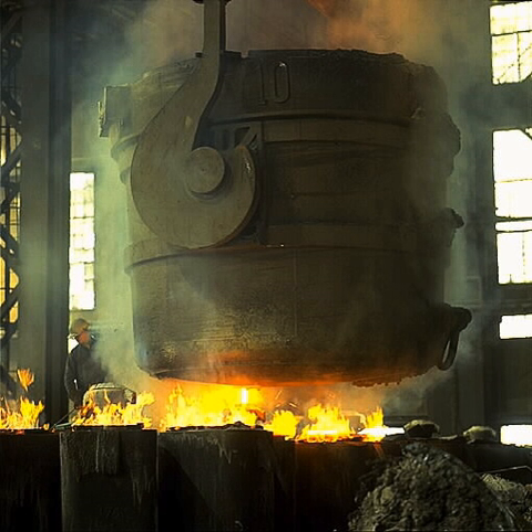Titanium is added as a degasser and deoxidizer, but it also increases fluidity. 0.15 to 0.5% vanadium is added to cast iron to stabilize cementite, increase hardness, and increase resistance to wear and heat. 0.1 to 0.3% zirconium helps to form graphite, deoxidize, and increase fluidity.